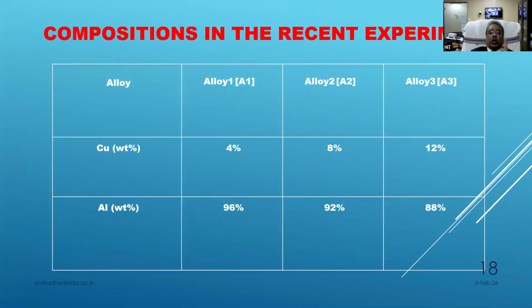Now if you see, this is alloy number 1, which we nomenclated as A1. Then alloy 2 is A2. Alloy 3 is A3. What is the difference? The alloys have only a trace amount of silicon, below 0.001. So copper is 4%, aluminum is the rest. Alloy 2 is 8 and 92, alloy 3 is 12 and 88.